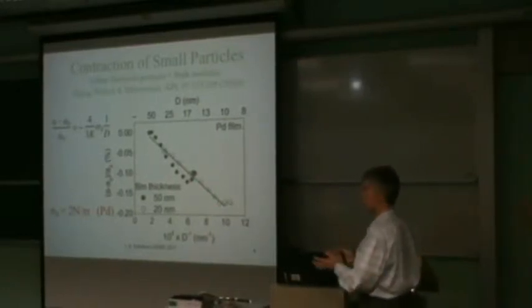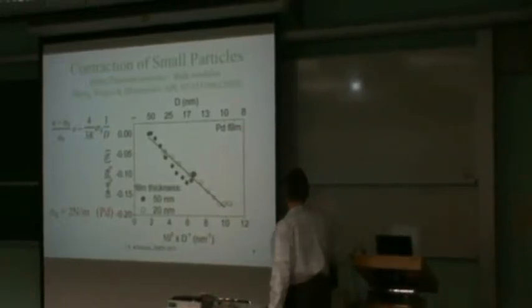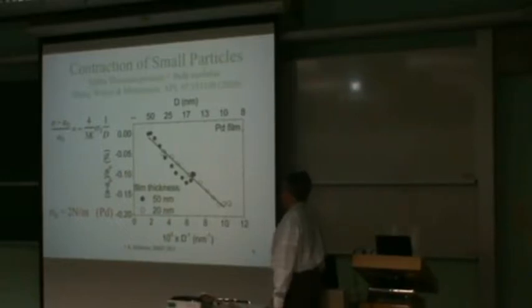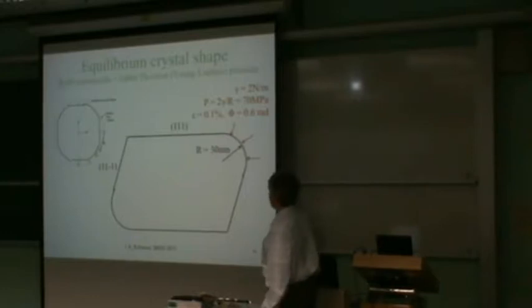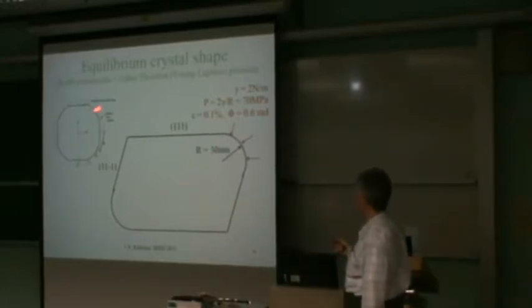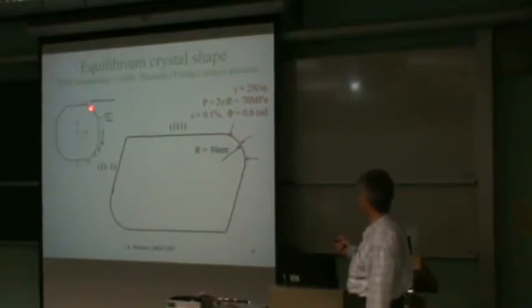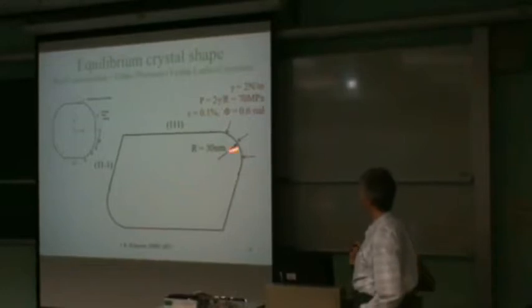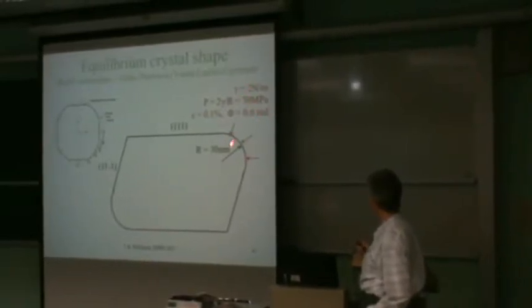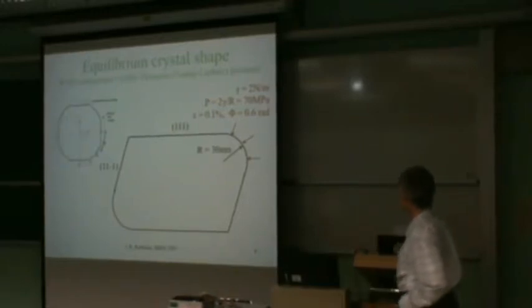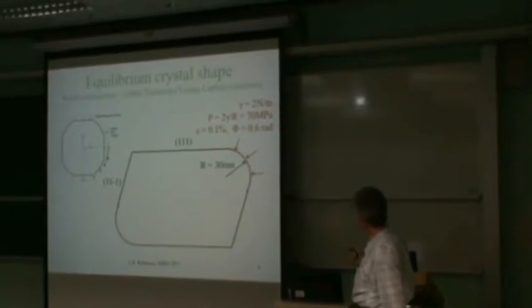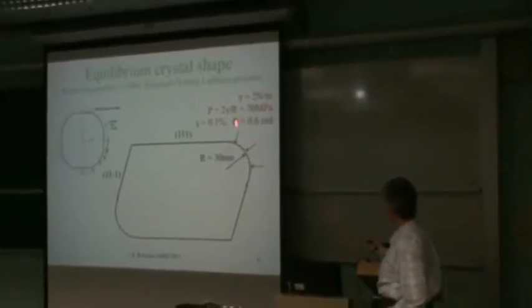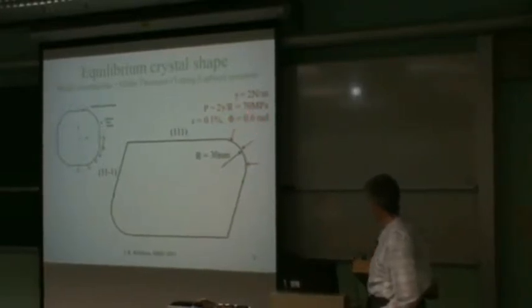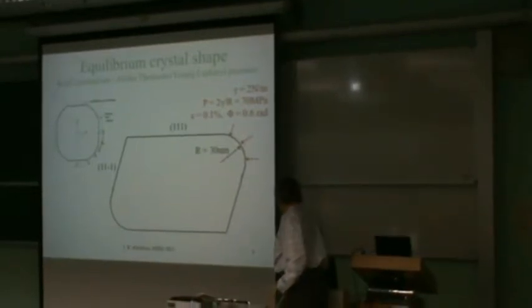So this shows that small particles will undergo a contraction just due to the surface tension, surface stress, which is surrounding them. And again, for small particles, that will show up as if you have a typical situation where you get the equilibrium crystal shape, you get some flat regions and some curved regions in general in the equilibrium of some small object. And the curved regions will have a pressure difference across them due to the surface stress, but acting through the Gibbs-Thompson effect. That will give a pressure difference, which will give a compression of the material inside the curved region. And to anticipate the readout that I'm going to be talking about later on, that would correspond to a phase shift of 0.6 radians, but we'll see a little bit later where that comes from.